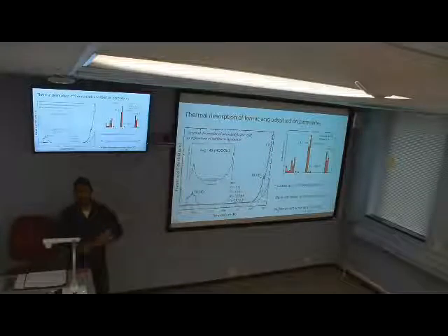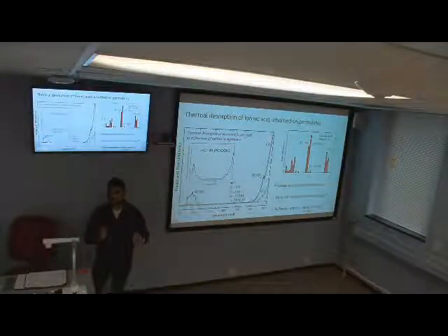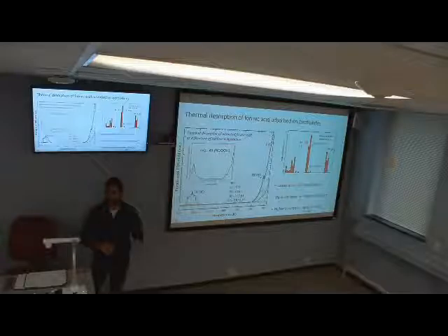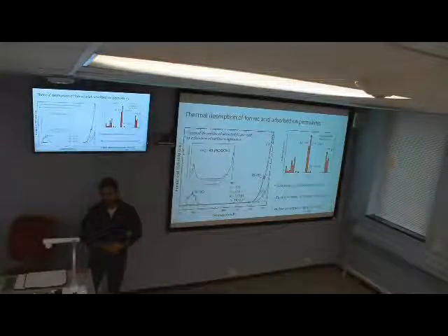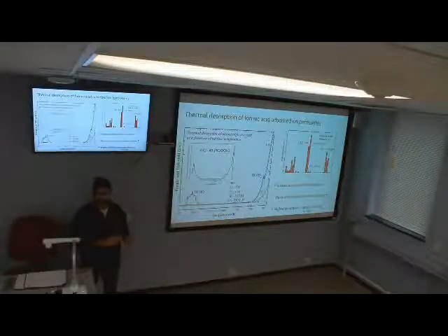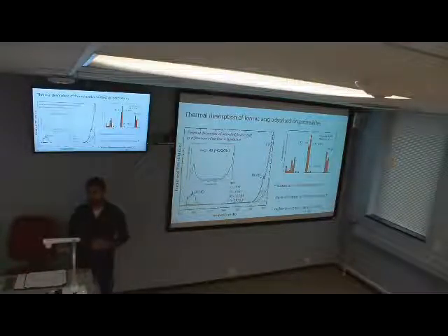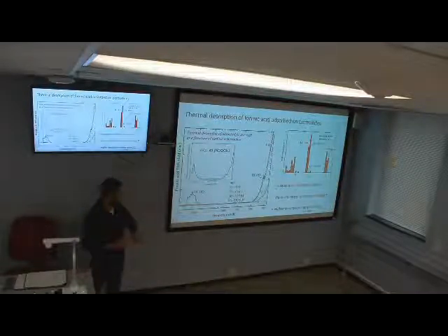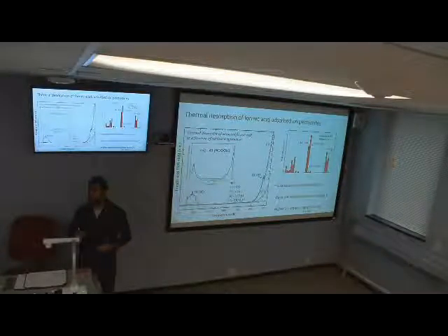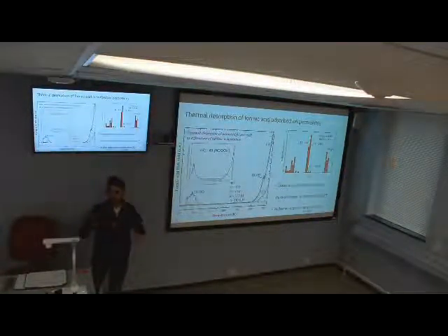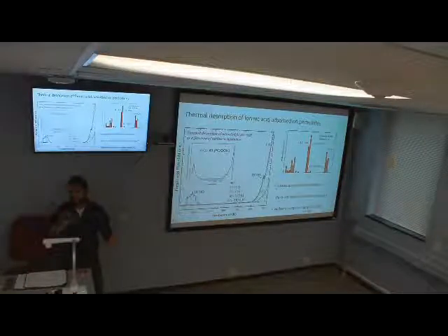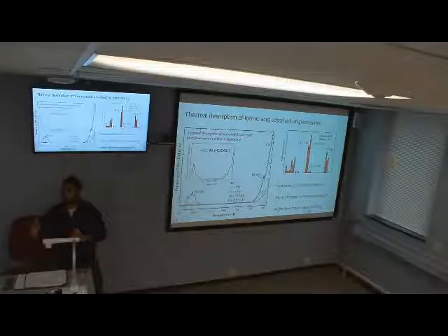So if we want to do both, then we have the dissociation fragments of formic acid, but if we want to detect the desorption fragments of the perovskite layer, we need to do a different experiment. So we can simply synthesize the perovskite layer and adsorb a formic acid layer like this, and then we can try to desorb it. We can just do the thermal ramp, and we can detect those dissociation fragments of formic acid, and we can see at which temperature those fragments are desorbing.